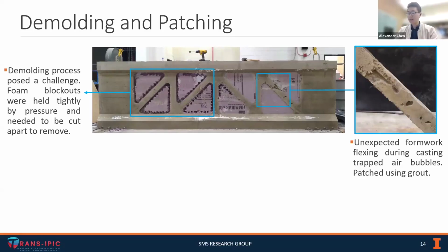On this side, you'll see that there are some voids in a diagonal member of the truss. And this was the location in the previous slide where I mentioned how a portion of the formwork began to flex under the pressure of the concrete. So that movement of the formwork sucked in a couple of air bubbles at that location. Fortunately, it was very easy for us to just patch this up once we fully demolded the specimen.